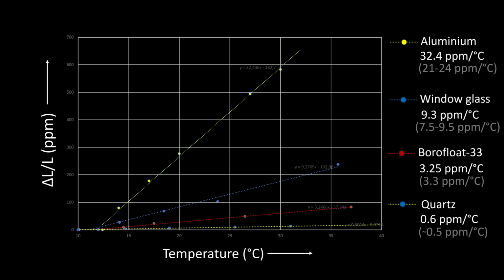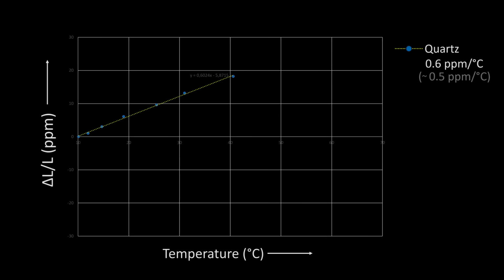Now the last value I want to show you in this graph is quartz. Here I measured a value of 0.6 ppm per degree Celsius, which is in agreement with the approximate value of 0.5 ppm from literature. So in general I would say that the measurements indicate that this setup is working as intended. Okay, so let's move on to the glass ceramics.